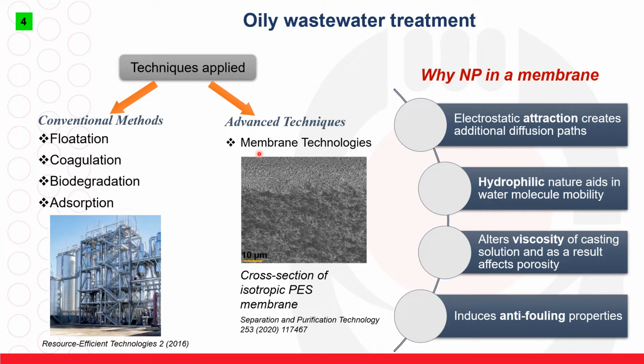But they have a limitation of fouling, whereby the contaminants in the wastewater block the water channels, and hence researchers have decided to embed nanoparticles in membranes to enhance their properties. Of course, when nanoparticles are embedded in membranes, they create electrostatic attraction, which creates additional diffusion paths. Some nanoparticles are hydrophilic in nature and hence increase the water mobility. Some nanoparticles also change the viscosity of the casting solution, which enhances the porosity of the membrane, and also they have been found to induce anti-fouling properties.